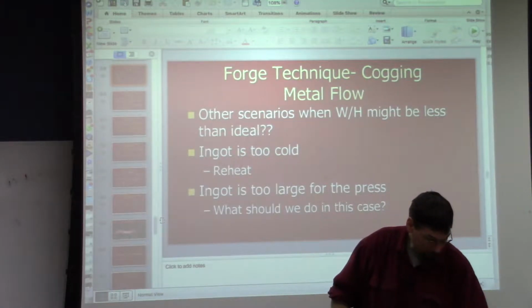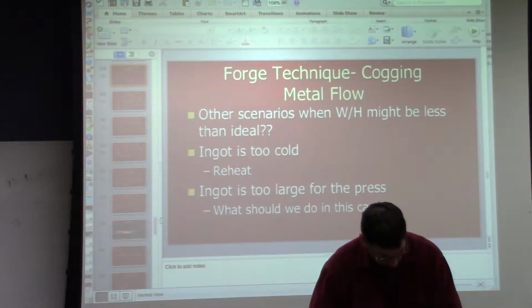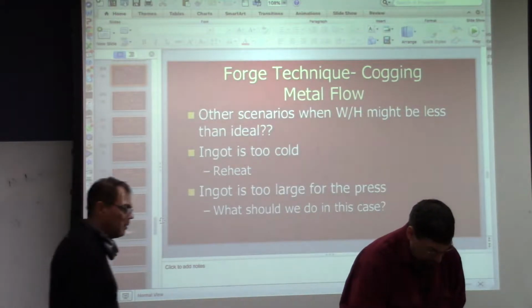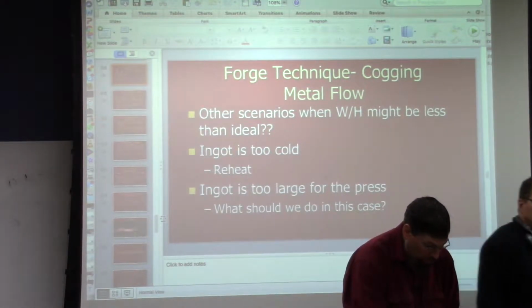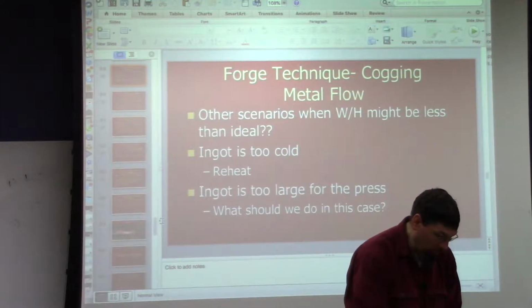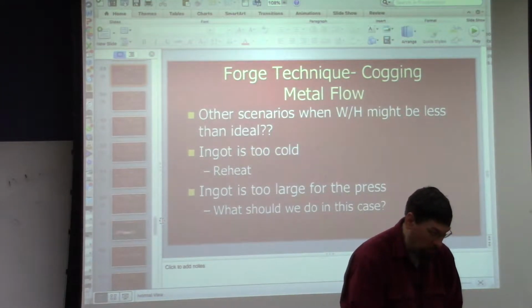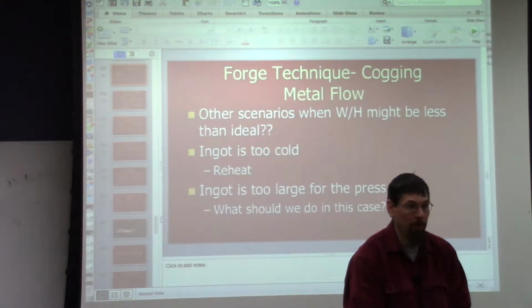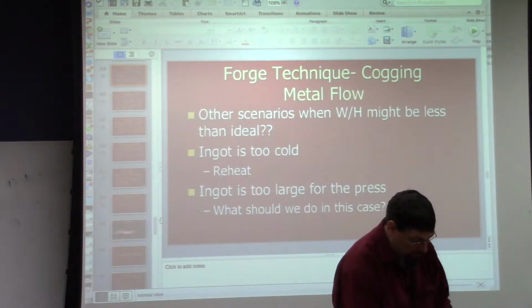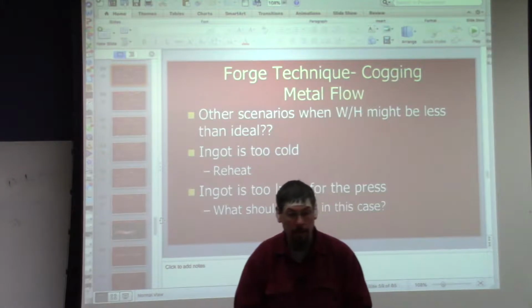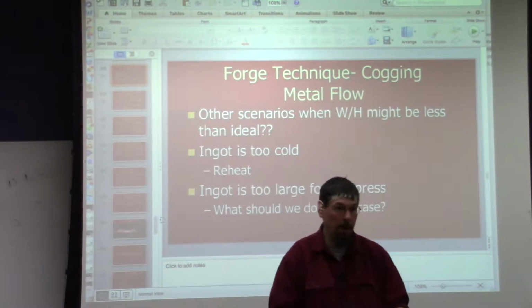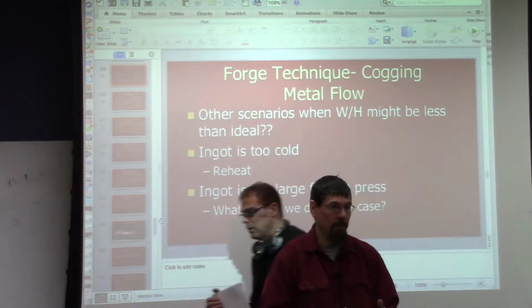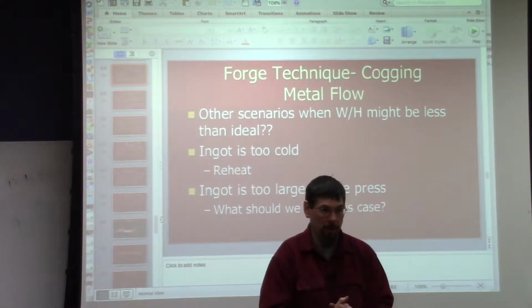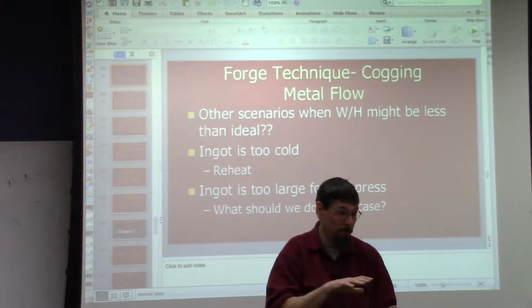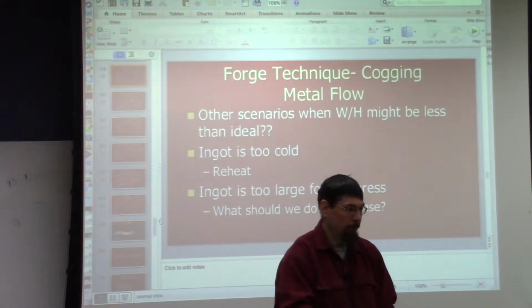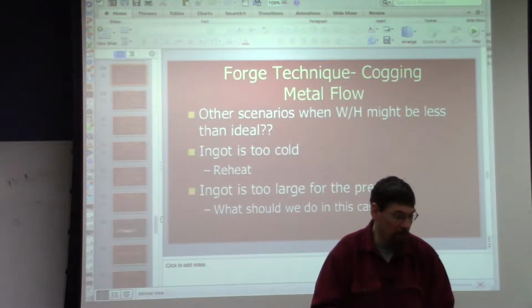And if you look carefully, you can actually see where some of these dendrites have grown out into free space. The other thing I brought here is a block. This is from a 400 series stainless steel, and we've got a whole bunch of holes in it. So this illustrates a really severe condition of what can happen when you don't do your forging properly. In this particular case, specifically, they took an ingot, and they did a little bit of upsetting to it, but nothing like the 50% upset that we talked about two weeks ago as being the minimum that you need to close up holes. So they did maybe 25% or something, a real minimal amount.